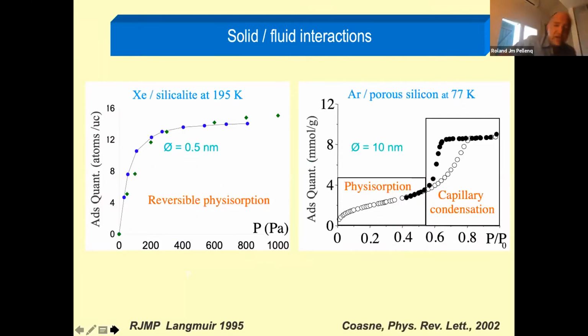Now coming back to differentiate between nanoporous and mesoporous, for instance xenon in this zeolite silicalite. The blue points are my simulation, the green the experiment. You can see we can easily predict this, and there's nothing heroic in that, because silicalite is a crystal—you just download the crystal atomic positions and you're done with the simulation basically.